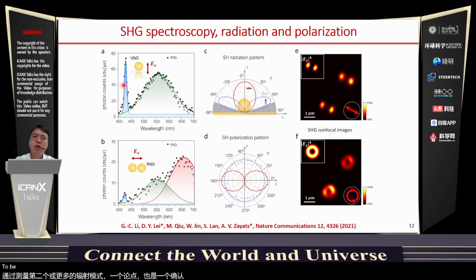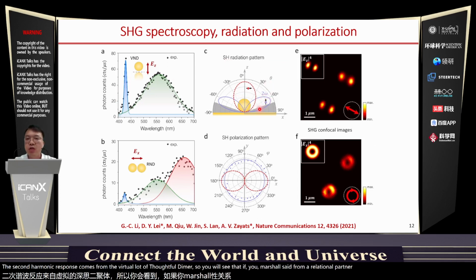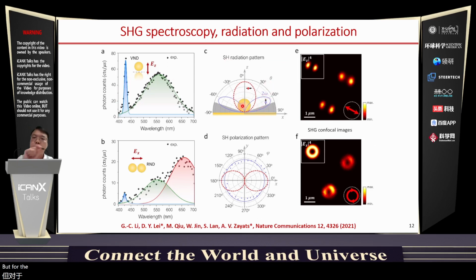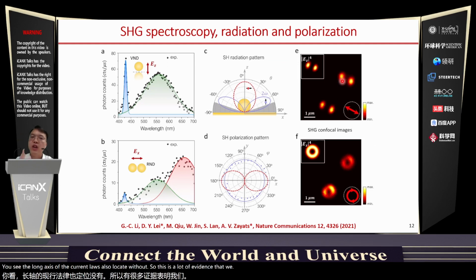So because in this particle on film system, the second harmonic response comes from the virtual nanoparticle dimer, you will see that if you measure the second harmonic radiation pattern, you will see such donut shape. But for the real nanoparticle dimer system, you will just see a solid spot. Okay, and this is also consistent with the second harmonic polarization pattern. And to further confirm that, you can rotate your excitation polarization. For example, you rotate that, you will see the long axis of the two lobes also rotate with that. So this is another evidence that we excite the vertical bonding dipolar mode in the particle on film system.